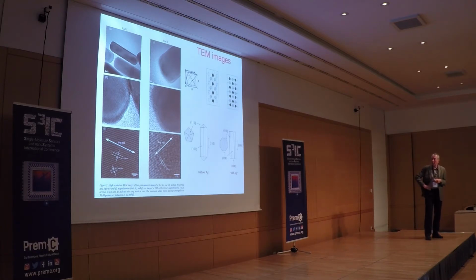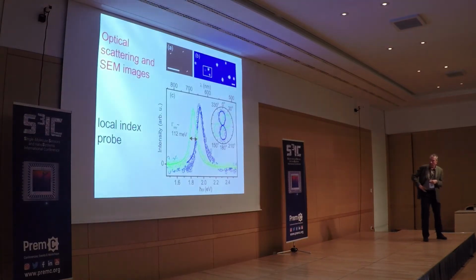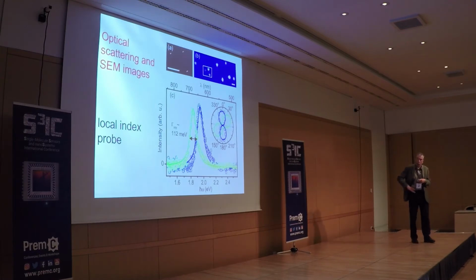nanoparticles. I should stress that this is not always the case for the sputtered or nanofabricated gold particles, because they are polycrystalline, they have many grain boundaries and defects, which makes the conducting properties not as good. So by using chemistry, you can really have a much nicer crystallographic quality than using physics in this case. You would expect usually the opposite, but in this case, it's not what happens. All right, and this translates into a very nice and very narrow sharp resonance.